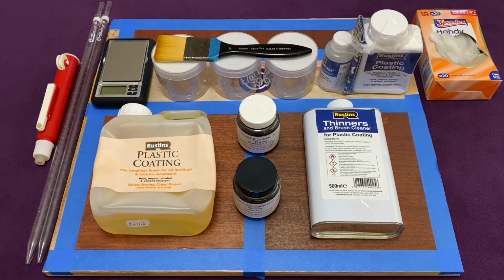Now, I've seen on internet forums that several users quote some personal experience or advice they received from Rustins technical support, which confirms the fact you either have to apply up to 3 coats within 2 hours to achieve the window for a chemical bond, I'll discuss more about that shortly, or wait several days for each previous coating to fully harden to ensure that you're going to get a satisfactory mechanical bond between each coating. The risk is if additional coatings are applied between these windows, you can risk trapping the solvent in the mixture that's hardening, and that causes the layers below to soften and wrinkle.